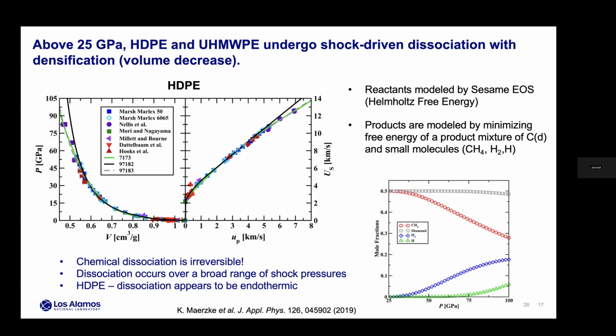And in fact, we have done some related experiments again at light sources looking at products, and it turns out that those bonds may be formed, and when you release it from the shock state, there actually could be a freezing temperature where you basically freeze out chemistry. So we've seen that as carbon clusters grow, there's a freezing temperature as you release it from the shock state. And if you get below that freezing temperature, you essentially lock in the chemistry, or you lock in the cluster size. So there's so much rich work that can be done in this area. It's hardly known what's going on. So we're trying to make a dent in it, but there's a lot to be learned in this area. Thank you.